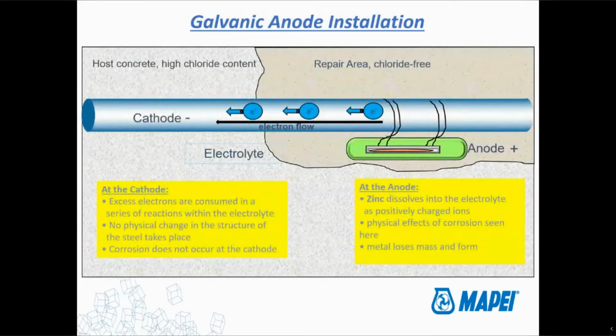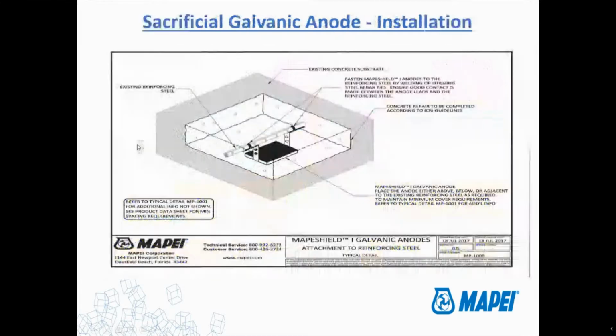So when we go back to this image, instead of the repair area turning into the cathode and then creating an anodic area around the exterior, you're keeping the anode inside of the patch, in that galvanic anode. The steel on the outside of the patch remains cathodic, continues to accept those electrons, and it does not corrode, and then you don't get that cracking and spalling immediately around the patch area. So a really good idea. They're not very expensive relative to the savings that you get out of using them.